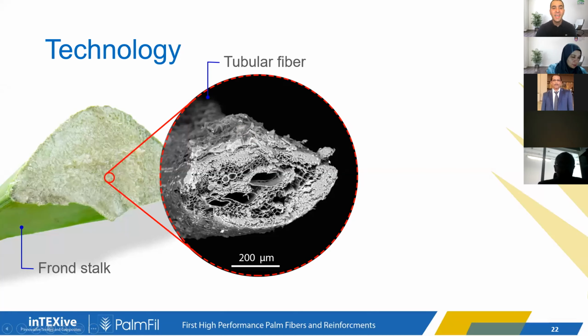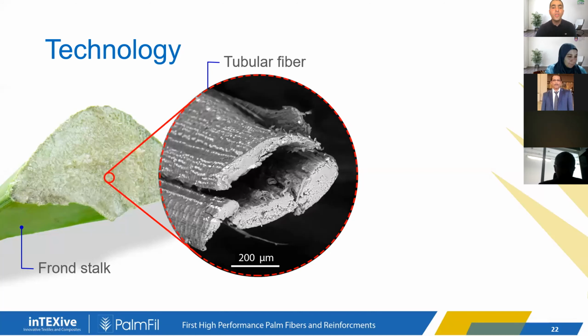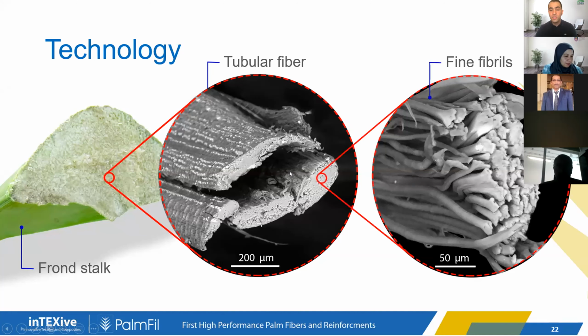So the purpose here was to eliminate this natural glue, and also to eliminate the void content and split the tubular fiber into longitudinal segments, because this tubular structure provides very high rigidity to the fiber, so you cannot twist it or bend it, it will just break. So this is why we need to split the fiber into longitudinal segments, and afterwards continue to fibrillate those fibers into the elemental microfibrils, but most importantly, without causing any damage or breakage to those fibrils.